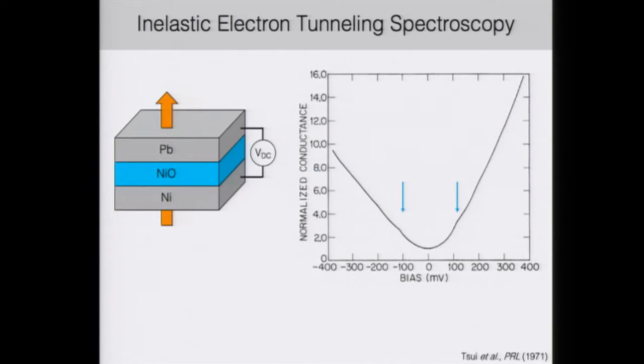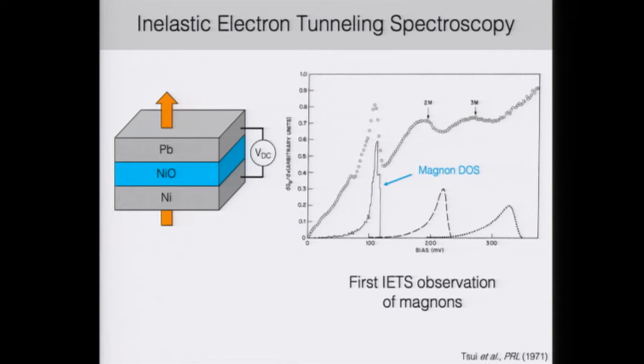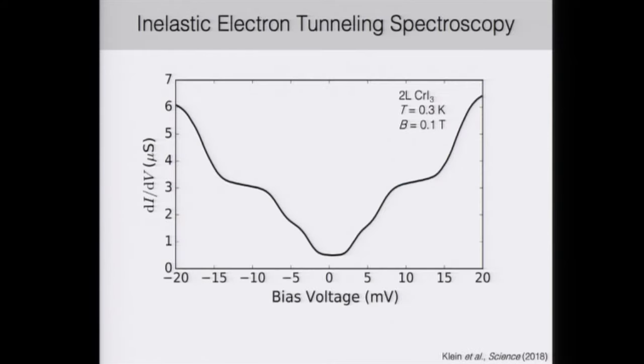So back in the early 1970s, researchers looked at a nickel oxide magnetic tunnel junction, and they noticed these little humps in the inelastic electron tunneling spectroscopy. And when they overlaid it with the magnon density of states, they realized that they're actually observing magnons in their tunnel barrier of nickel oxide. So if we take a look at our own tunneling data, then we can actually see that it's quite similar.